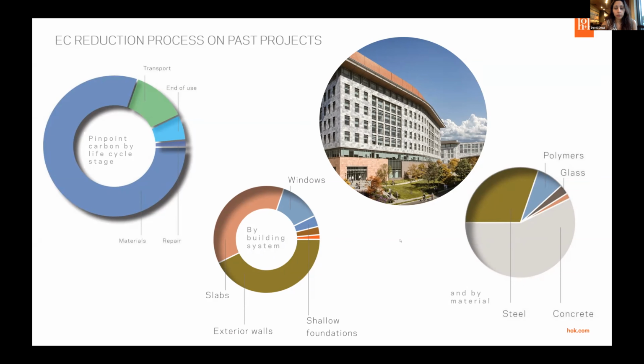Oftentimes, even with steel superstructure buildings, concrete can be the majority of the embodied carbon because of cement being such a high embodied carbon material, and foundations representing a very large percentage of the total structural material quantities. Also important to note, if you're looking at the facade versus the structure, it's very often 45% to 50% facade and maybe 60-65% structure. So it may seem like the facade would be insignificant compared to the structure in terms of the carbon breakdown, but it really isn't. It can come very close to 50-50. And in the facade, if you're looking for the low-hanging fruit, aluminum components are typically the low-hanging fruit. Yeah, so we can go to the next slide.